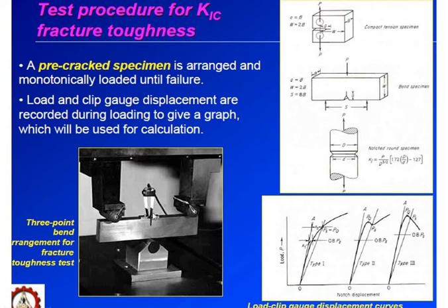You can also relate this to the bend test. When we fit the bend specimen, if you look at the bottom, they have placed it for testing. At which points do we fix the rollers? Between the 2 points where you are going to fix your rollers, the distance is given by S, and that is equal to 8 times your thickness, that is 8B.